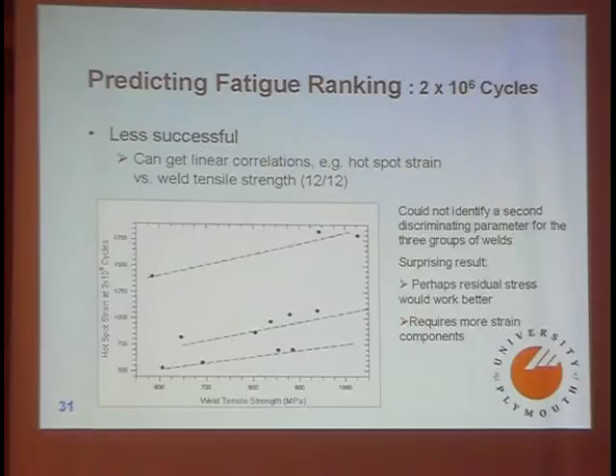When you come to 2 million cycles, it's less successful. You can get linear correlations in the data, e.g. hotspot strain versus weld tensile strength, which will give you these correlations for 12 out of 12 welds. What we can't do is identify a second discriminating parameter that will allow us to predict which line the data should lie on. Now, it is possible that residual stress would work better than residual strain here, but that would require more measurements. But that's a quite likely supposition.